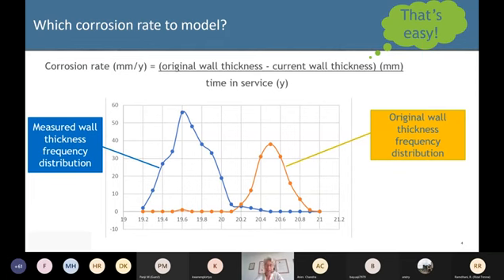Steel is not uniform. To give you an example, in this data the axis at the bottom is the thickness of steel in millimeters, and it's a frequency distribution. So what we've got is the number of incidences on the vertical axis. What you can see with the orange graph is that steel, when you buy it, has a certain distribution of size of the wall thickness, and this sample is real data. It comes from a couple of hundred readings taken from some actual pipe, and the orange represents the, let's say, uncorroded wall thickness of this piece of pipe, which is plate steel. It's rolled steel. Now, I can assure you that some products will be very much broader distributions.